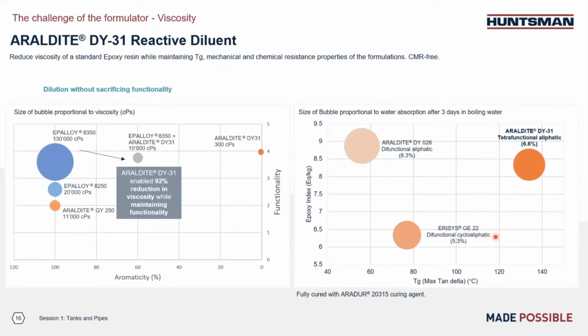And you can see, using Aradur 20315, kind of an IPDA-based curing agent, the ultimate TG with the DY31 system can get very close to 140 degrees C. With only 2 functionality, the DY026 TG is even below 60 degrees C. And with Erisys GE22, because it's a cycloaliphatic structure, it will improve the system TG, but it's still lower than 80 degrees C, the final TG.